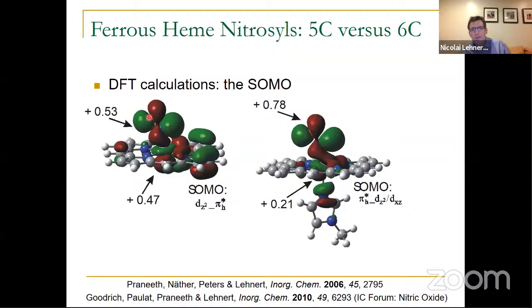Now in the 6 coordinate complex, you can see that there indeed is a pretty dramatic change in the property of this orbital. The first thing you notice is that the interaction with the dz square orbital becomes much smaller. In the 5 coordinate complex this orbital is about 50-50, but here the contribution from dz square is smaller. You can also see that instead of standing up straight, it's tilted away a little bit from the NO ligand. So this sigma bond becomes a lot weaker in the 6 coordinate complex.